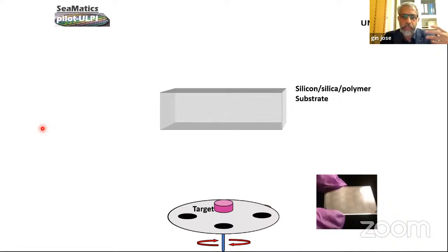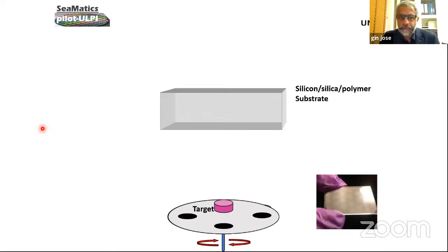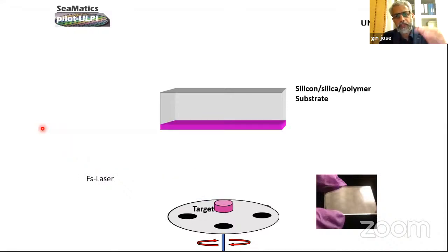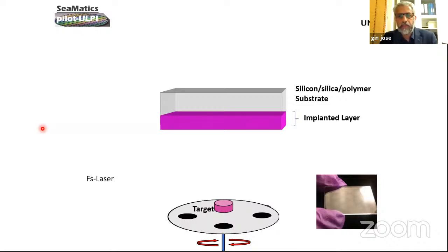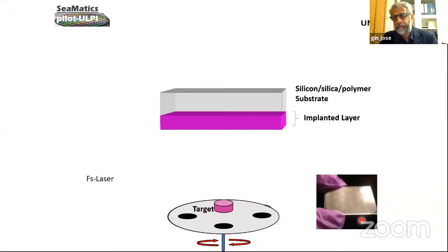The difference from a typical deposition process: normally when you paint a surface, you form a thin layer on the outer surface. Here, we make the material diffuse into the substrate — creating a layer that goes into the glass. Running this process for a longer time produces thicker layers, modifying the surface layer of the silica glass. Using a mask, the material can be implanted only onto certain areas.